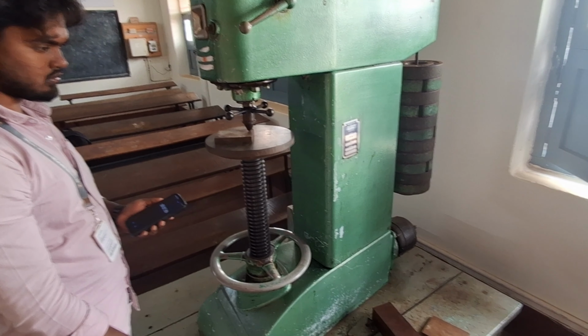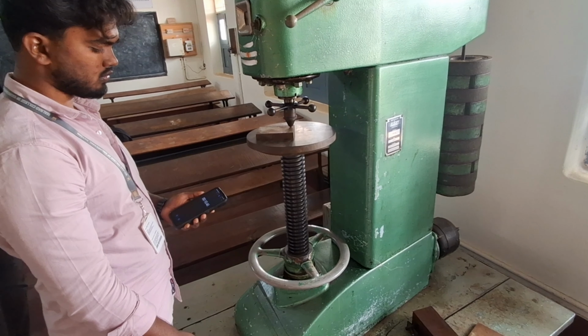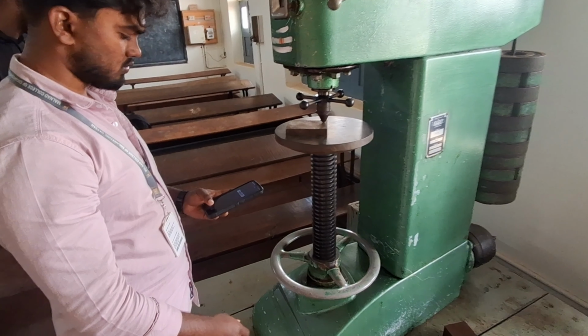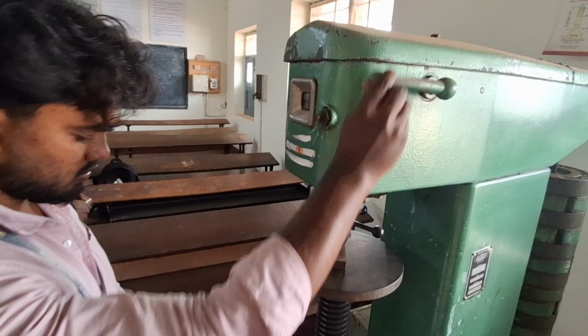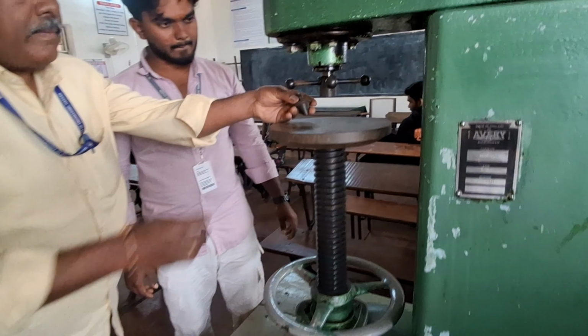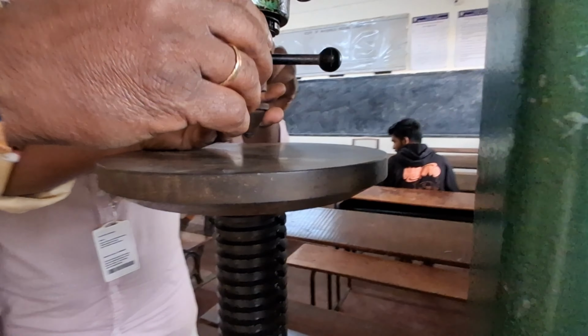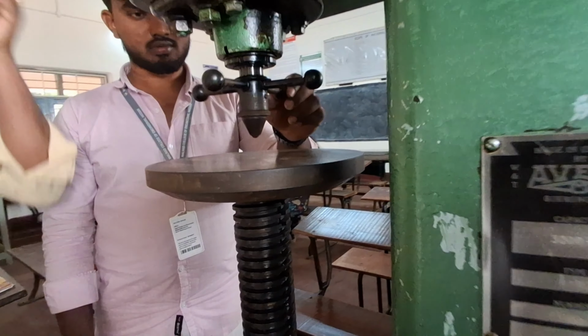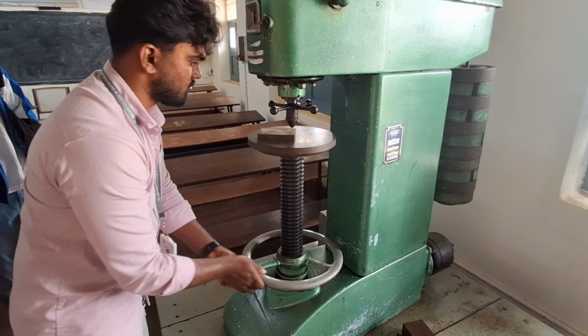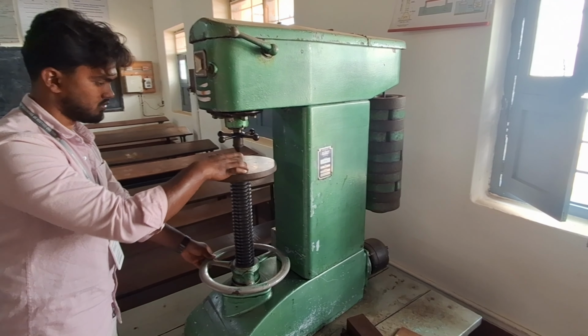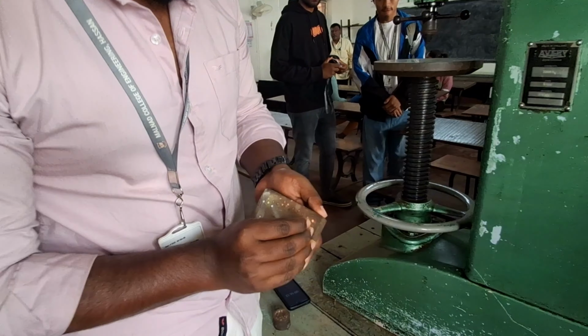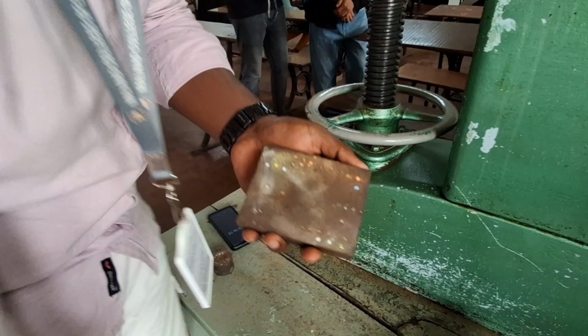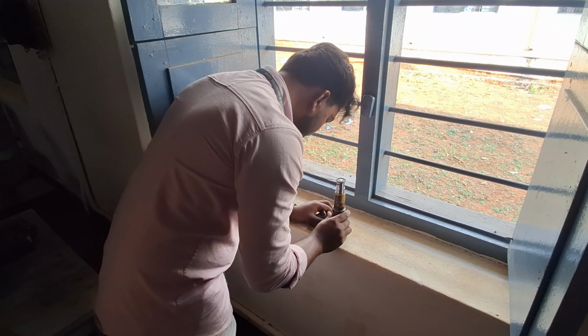The same procedure followed for the non-ferrous material is repeated for the ferrous material, with a change in ball diameter and applied load. For ferrous materials, a 10 mm steel ball is used. A higher load of about 3 tons is applied. The load is maintained for about 15 seconds as per laboratory testing conditions. After unloading, an impression is formed on the surface of the ferrous specimen. The diameter of the impression is measured using the Brinell's microscope. The observed readings are recorded in the tabular column. Using these readings, the Brinell hardness number of the given ferrous material is calculated.